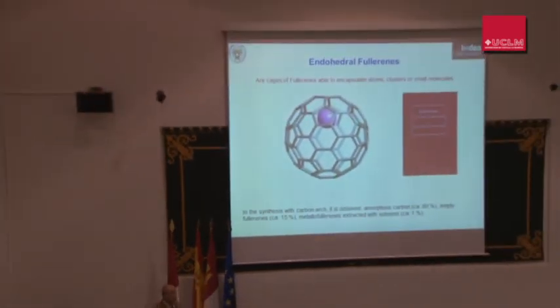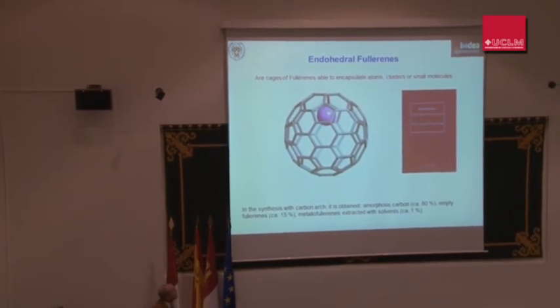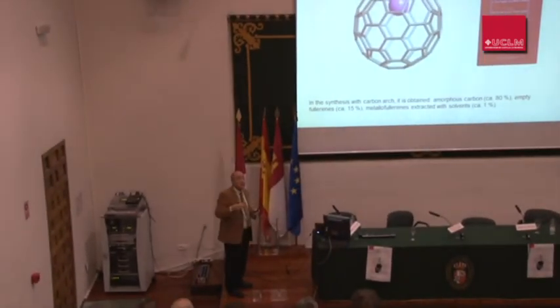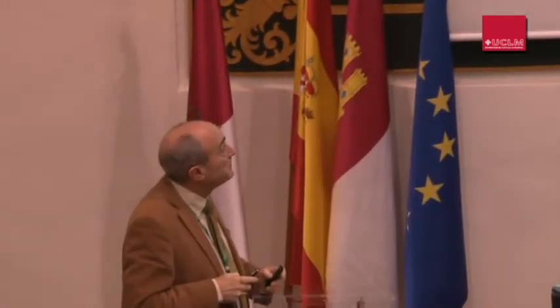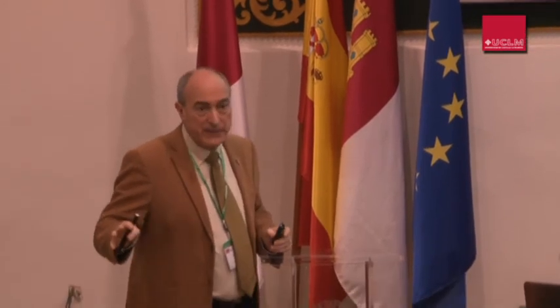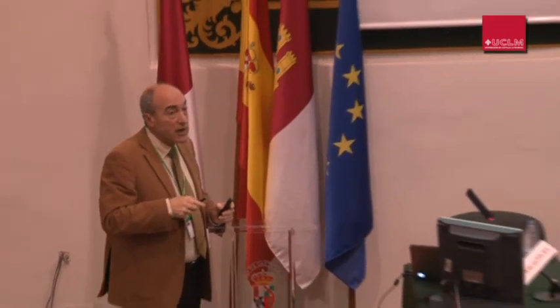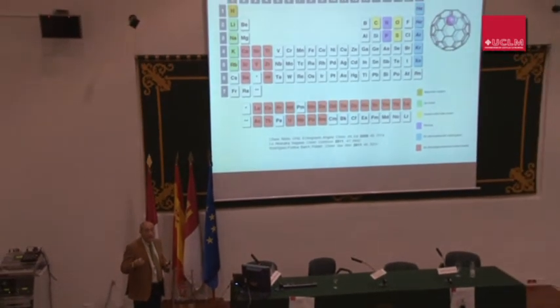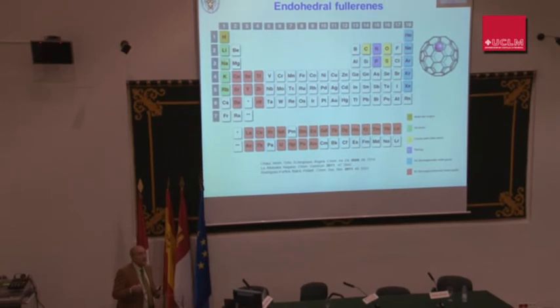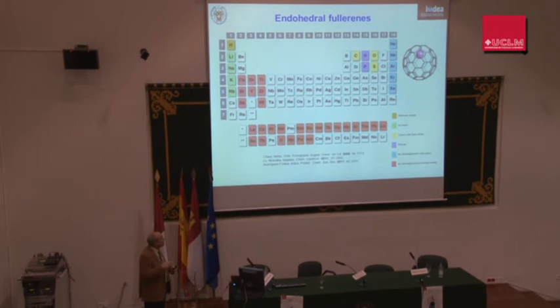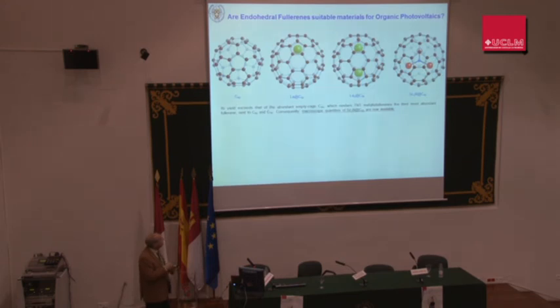Typically, these compounds, which are beautiful, by the way, are carbon cages, incarcerating atoms, clusters, or maybe small molecules like water, hydrogen, and so on. So people could consider that these are rare species, but after C60 and C70, the scandium nitride endohedral fullerene is the most abundant fullerene. Actually, with gadolinium inside, for instance, for imaging purposes, people are preparing kilogram amounts. All those colored elements mean that they have been introduced, incarcerated within the carbon cage, by following, of course, different strategies, which I will not mention today. But let me show you that, for instance, lanthanum C82, lanthanum 2 C80, or scandium nitride C80 are endohedral materials which are completely different to C60.